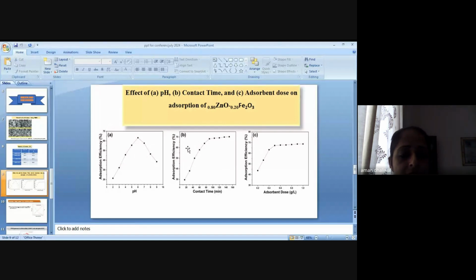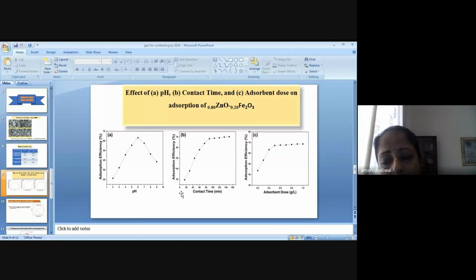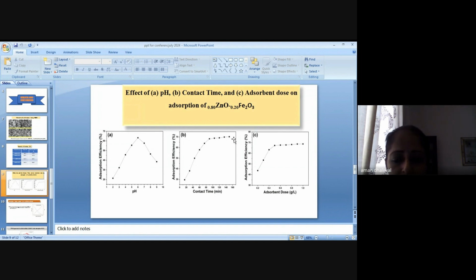And in the second graph, for the contact time, the adsorption efficiency was evaluated by applying 25 milliliters of the uranium solution prepared in the lab at a dose of 0.5 gram per liter for a time between 15 to 150 minutes. In the beginning, the adsorption percentage rose from approximately 29% to 68%. After that it stays almost constant. So this time was taken as 90 minutes, where the maximum adsorption efficiency was measured for the uranium ions.